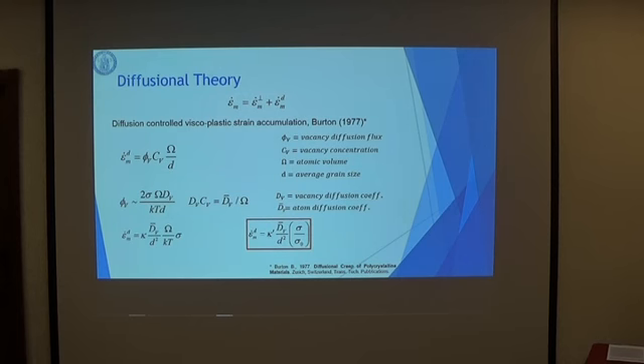So, the minimum creep rate can be seen as a sum of two contributions. The first one is the dislocational contribution, and the second one is the diffusional one. Then, considering the Burton equation related to the diffusion theory, we have that the minimum creep rate for the diffusional contribution is proportional to the product between the vacancy diffusion flux and vacancy concentration, times the ratio between the atomic volume and the average grain size. If we make explicit the dependence of the vacancy diffusion flux in terms of vacancy diffusion coefficient and atom diffusion coefficient, we have this equation in the boxed lines.